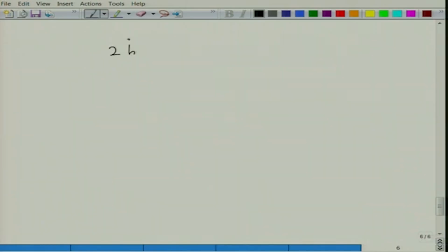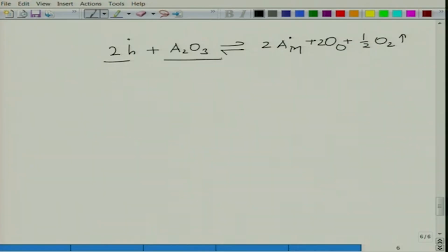Okay. Alternatively, if you have, let us say, holes in the system or electrons in the system, in this case if you had holes in the system, if the system had holes, then you again dope it with A2O3, then 2A go to M site plus 2O go to O site, and this becomes half O2. So, you can reduce the hole concentration by doping it with a higher valence oxide. So, basically you can reduce the amount of defects if your oxide was already defective. Okay. So, appropriately you can choose, for MO you will choose M2O3, but for M2O you can choose MO. Okay. Alternatively, if you wanted to control the metal vacancies, then you will have to go for lower valence stuff. So, that is how you do.